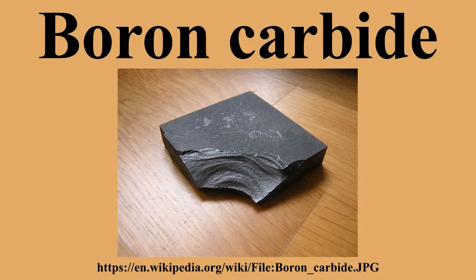Boron carbide is thus not a single compound, but a family of compounds of different compositions. A common intermediate, which approximates a commonly found ratio of elements, is B6.5C. Quantum mechanical calculations have demonstrated that configurational disorder between boron and carbon atoms on the different positions in the crystal determines several of the material's properties. In particular, the crystal symmetry of the B4C composition and the non-metallic electrical character of the B13C2 composition.